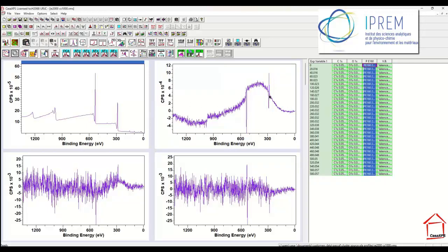And within this second abstract factor, we now see what is happening. While we did not see a significant change in the photoemission peaks, what was happening is a change in the background, and this change in the background is a consequence of having a sample that has a buried layer of silicon. So the photoemission from silicon is very small. The silicon 2s, silicon 2p, we do not see much in the way of signal in these data,